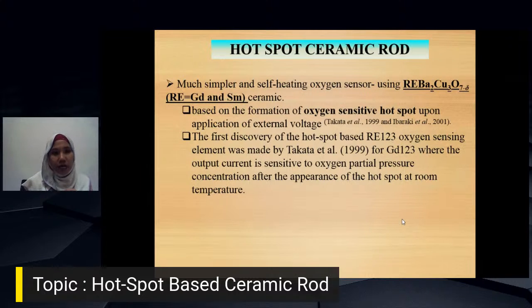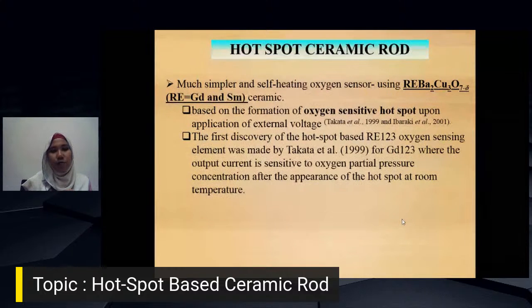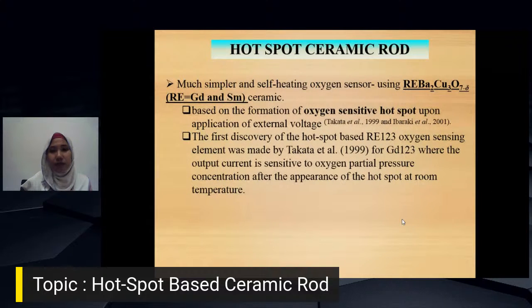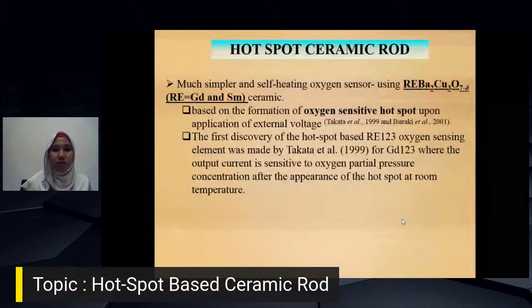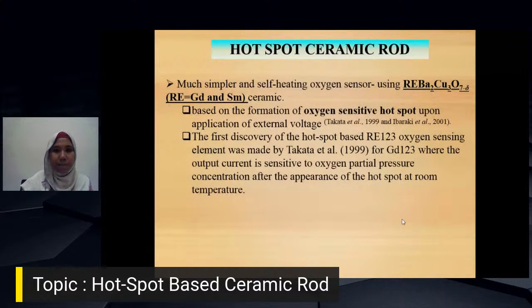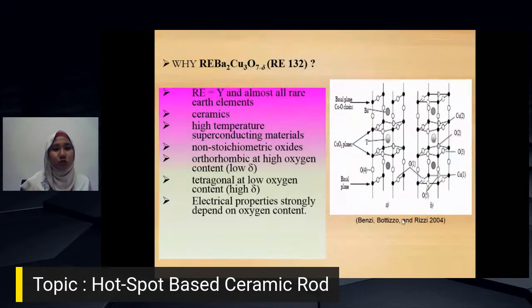For this phenomenon, the first discovery of the hotspot based Re123 oxygen sensing element was by the researcher Takata, for the element Re123, where the output current is sensitive to oxygen partial pressure concentration after the appearance of the hotspot at room temperature. This means the hotspot can sense the concentration of the oxygen partial pressure in the surroundings at room temperature. So why do we choose the rare earth barium copper ceramic material?